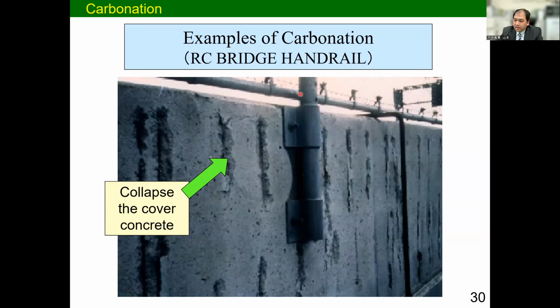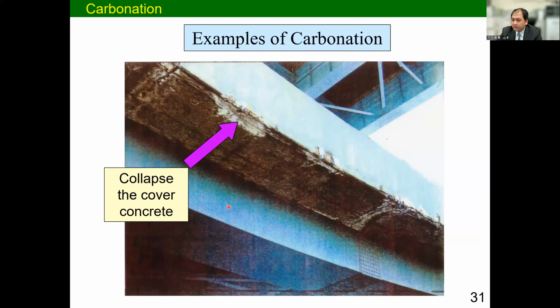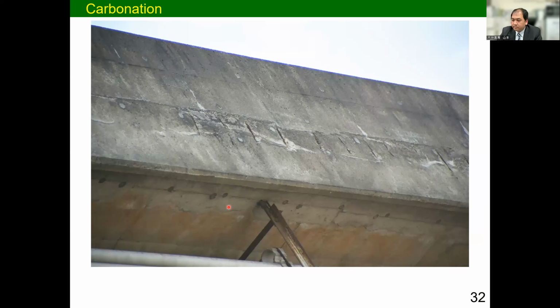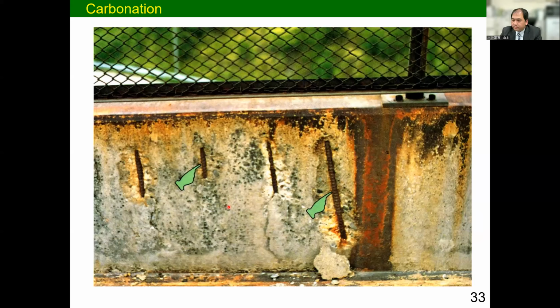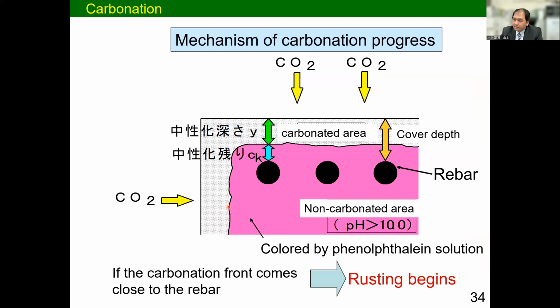Because of carbonation, the steel bar corroded. Then the covering concrete part spalled. This is also due to carbonation. This is also due to carbonation. If the carbonation area comes to the surface of the rebar, then the passivity film of the rebar will be destroyed and then start rusting.